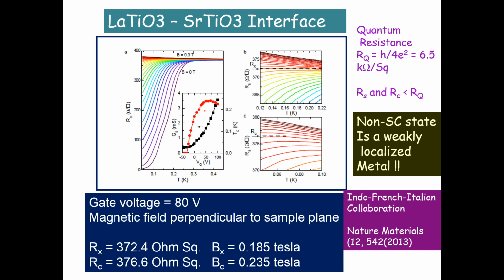But if I continue expanding this portion down here, I come to another region where again the resistance is reasonably constant in temperature over this range, from about 20 millikelvin to about 80 millikelvin or so. So this critical resistance Rc corresponding to this point is here, and the critical field is here. But we must remember that these values are much smaller than the quantum resistance for localization in 2D.